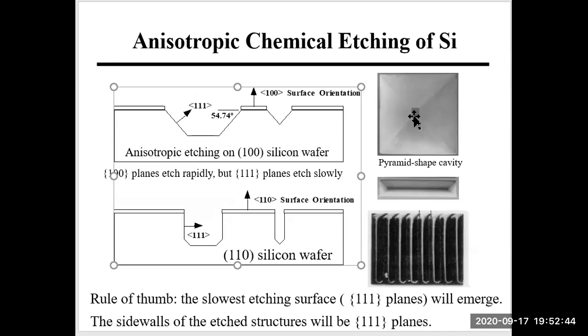Actually on 100 wafer, we can fabricate pyramid shape cavity or V-shape cavity or trench. These two are actually topside view, we view from the top of the wafer. So that's anisotropic etching on 100 wafer. The bottom figure shows anisotropic etching on 110 wafer. Now 110 wafer means that the surface of the wafer is a 110 direction or 110 plane. And we can see that trenches with vertical side walls can be fabricated on 110 wafer by using anisotropic etching.